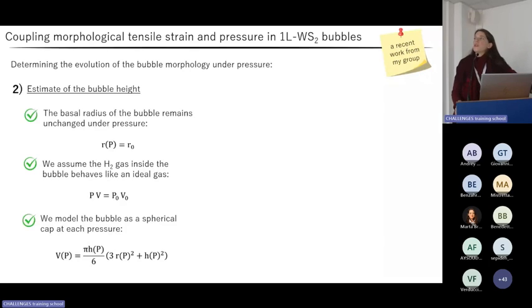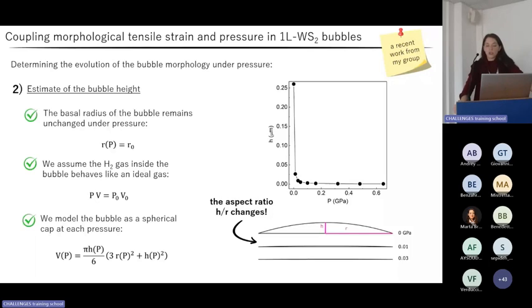Knowing the pressure evolution of the bubble diameter, we could also get an estimate for the pressure evolution of the bubble height, under the assumptions that the gas inside the bubble follows the ideal gas law and that the bubble at each pressure can be modeled as a spherical cap. Under these pretty reasonable approximations, merging the three relationships reported on the left, we could obtain this trend for the bubble height as a function of pressure, from which we see that the bubble height dramatically decreases under the application of pressure, leading to a great change in the aspect ratio of our system.